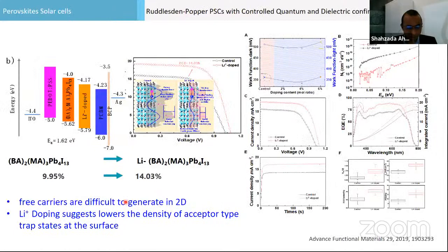Pure 2D, we are also studying a pure 2D based perovskite. Layered 2D is called layered perovskite, but the quantum confinement is very high because the charges are not coming to the collector, and they're not very highly efficient. So we used butylamine, we have doped with lithium, so it works. Efficiency increased to a very good 14%. These devices are very, very stable, with pure layered perovskite structures.